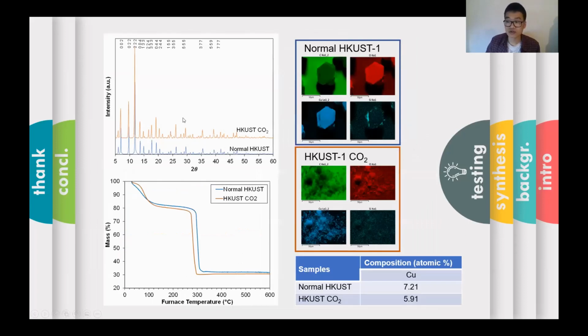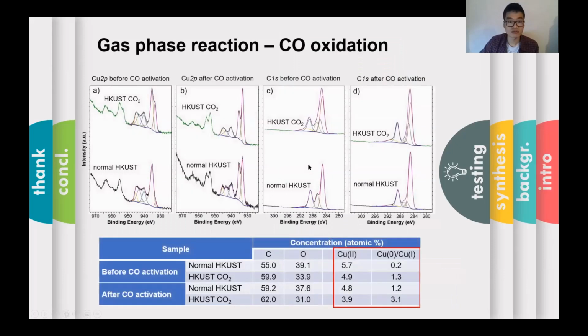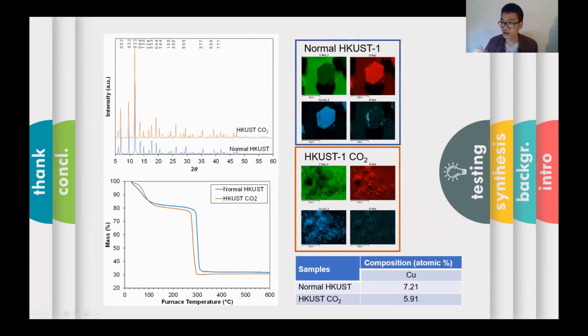This is also confirmed by the similarities in the XRD results of these two samples. We also notice that both samples start to decompose at around 280 degrees C, and the lower thermal stability of HKUST-1 CO2 might be due to the smaller particle size of this sample compared to the normal HKUST-1. And copper is an active site in HKUST-1 MOF, so we tested the elemental composition of these materials and noticed that the HKUST-1 CO2 has slightly lower copper content than the normal HKUST-1, which might be due to the defect formation in the CO2 sample.